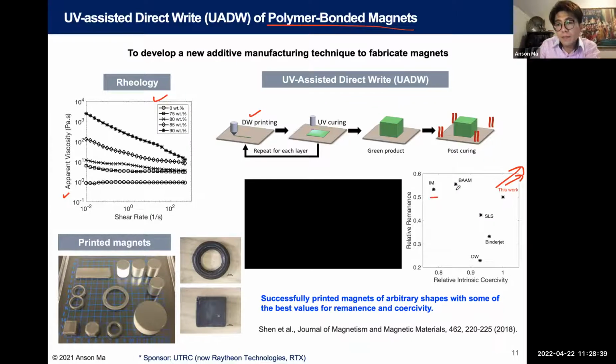These are different methods like injection molding, and this is a big area, additive manufacturing. This is selective laser sintering, binder jetting, direct ink writing. But we're doing pretty good with this method. We call this UV assisted direct write because we combine the direct ink writing process with UV curing. And to make sure that we have good shape fidelity for each layer after we print, we look at rheology, and we also combine this with UV.